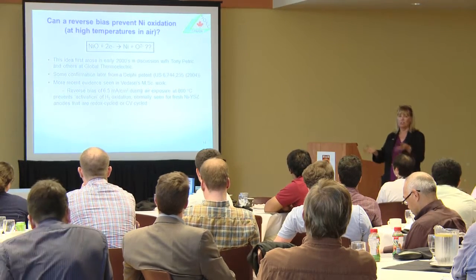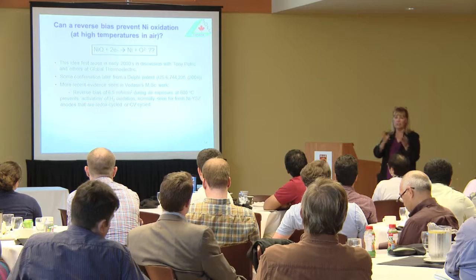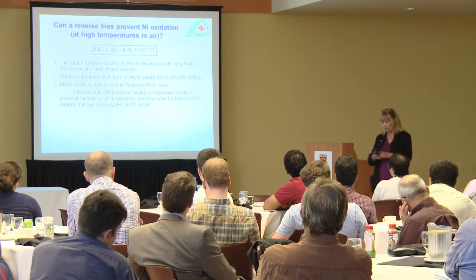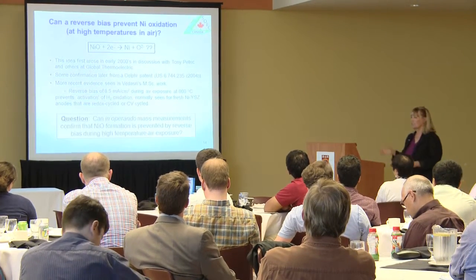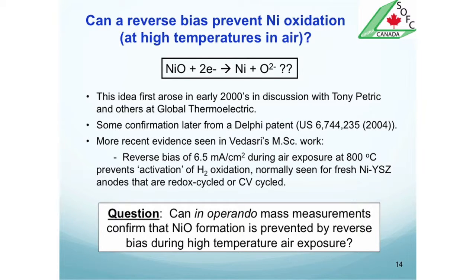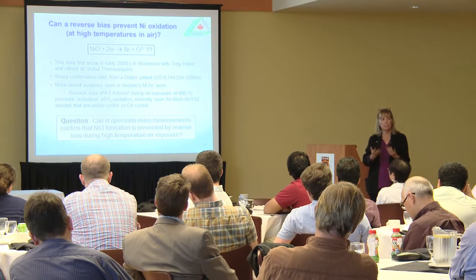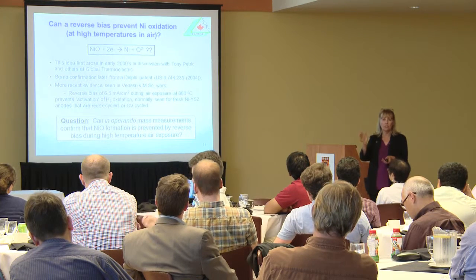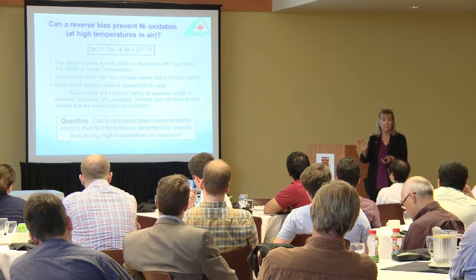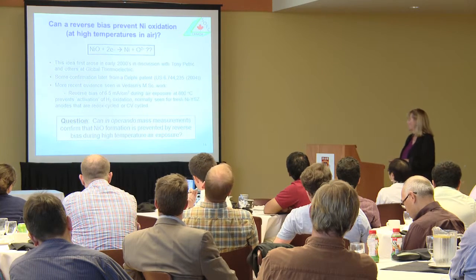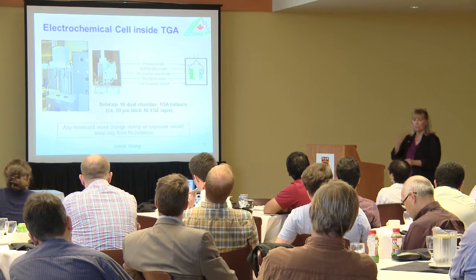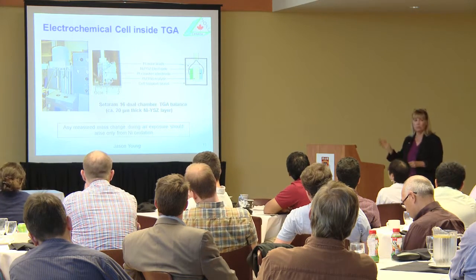And one way, you can quench and then try to look for oxygen. And it's hard, though. All the imaging studies are hard. So our goal here was, could we track the weight, the mass of the cell while we expose it to oxygen? And this is what we're trying. We would hope to see no mass change. That would mean there's been no nickel oxidation. Could we do that? So again, I have to give very good credit to Jason's great hands with instrumentation.